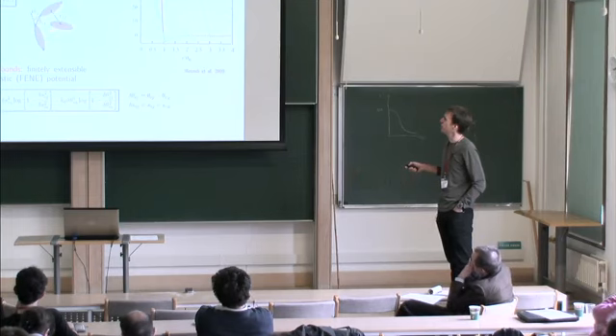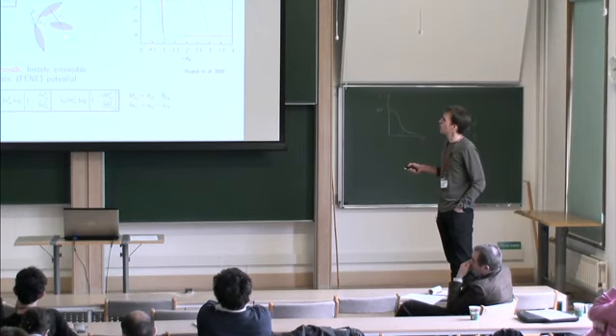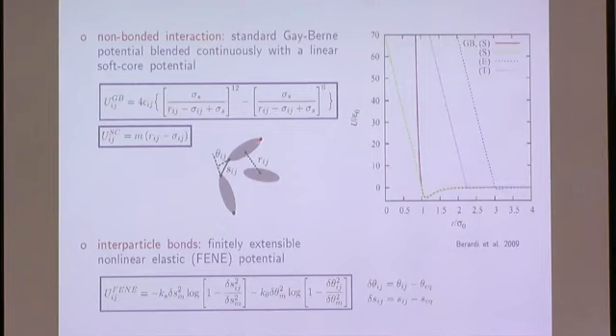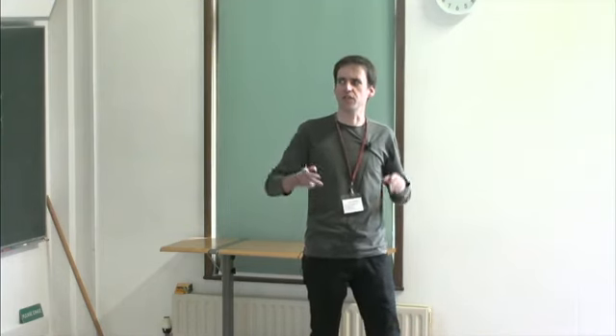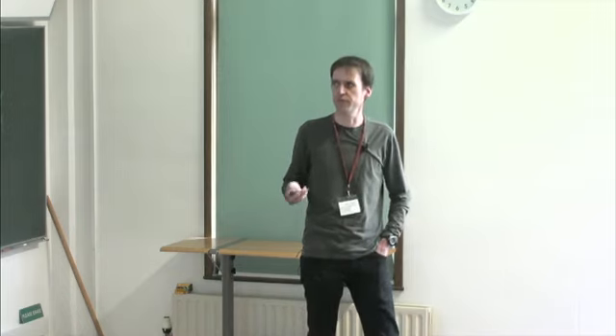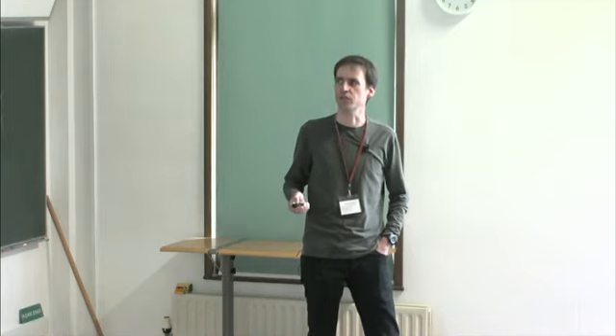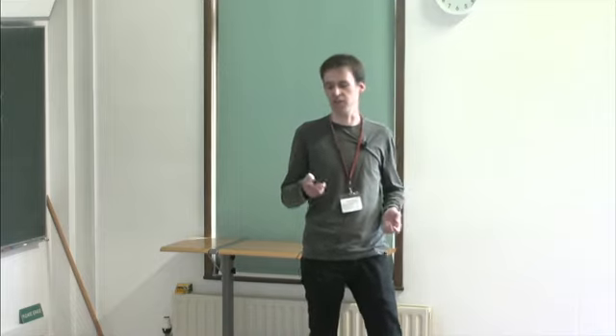In addition to having interactions between the ellipsoids themselves, we also have to bond the particles belonging to the network. The interparticle bonds here are modeled by the so-called finitely extensible nonlinear elastic potential, FENE. It's quite frequently used in polymer science. We applied it both to stretching of the bonds and to bending. In comparison with a Hookean harmonic potential, it penalizes large deformations more than the harmonic one, and also has a logarithmic divergence, which imposes some maximum deformation range. In other words, the elastomer we are considering here cannot be torn, it cannot break.